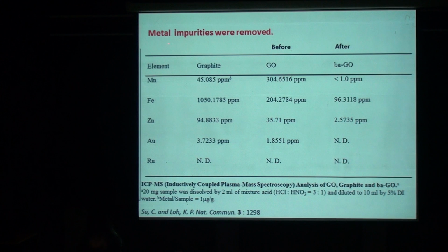And we do analysis to find whether there are any metal impurities. After the base-acid treatment, it can be seen that the manganese, which is important because we use potassium permanganate in the oxidation process, is reduced to less than 1 part per million, even less than the original graphite. And iron, zinc, gold, ruthenium, all the magnetic or non-magnetic metals are reduced to very low concentration. So the catalytic property is not due to the metal.